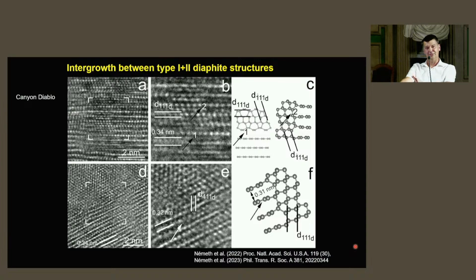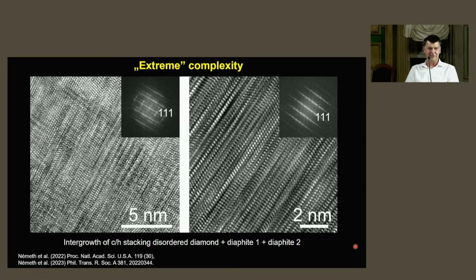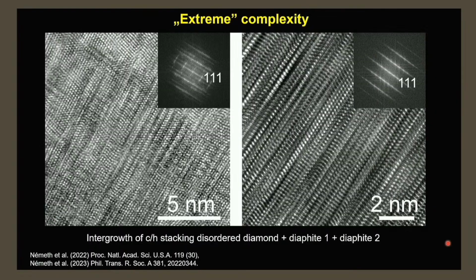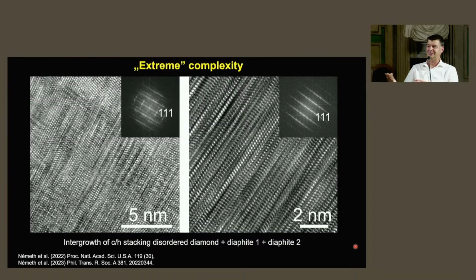But when you consider these different type 1 and type 2 intergrowths, and add the stacking disordered diamond, then you will see images like what I'm showing here, which almost doesn't show any periodicity. It's completely lost perpendicular to the layers. So it's essentially not a crystal with sharp diffraction. Essentially, it's difficult to categorize them. These images to me look like when, during crocheting, the knitting needle slips away in all directions. So anyway, these are examples from the Canyon Diablo diamond and show evidence for the intergrowths of these stacking disordered diamond and diaphite structures.